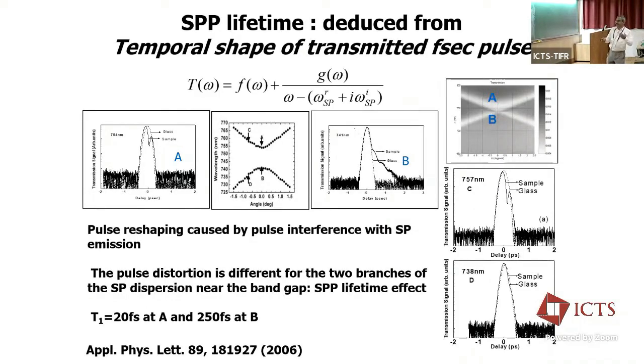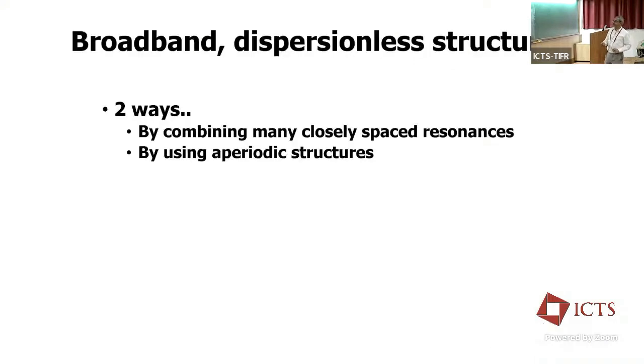This is reflected, for example, if you launch a short Gaussian pulse on a grating and look at the reflection or the transmission. Depending on the lifetime of the plasmon mode, whether you are exciting A, B, C, or D, you'll have different distortion in your short pulse. So from this, we showed how to calculate the plasmon lifetimes and other things, from the pure physics point of view. But if you want to use them for short pulse applications, we want to have broadband dispersionless structures. So we showed that there are 2 ways to do it.